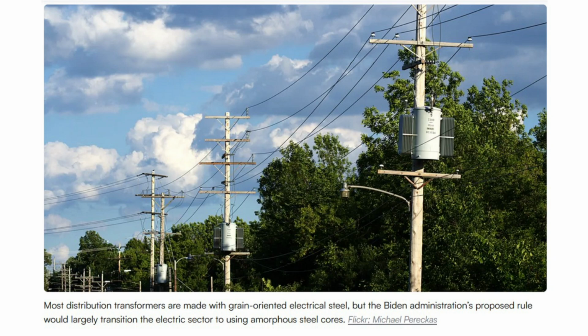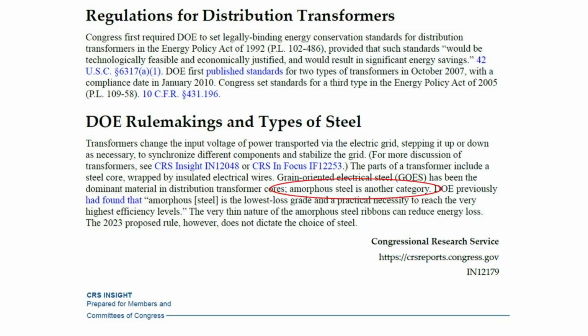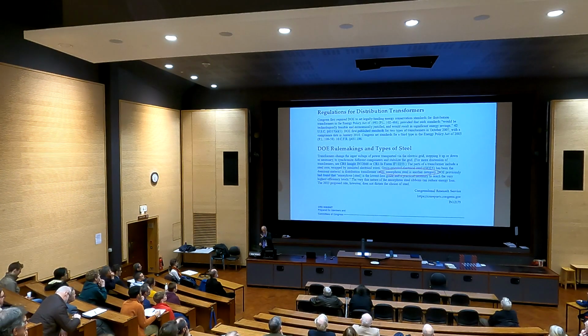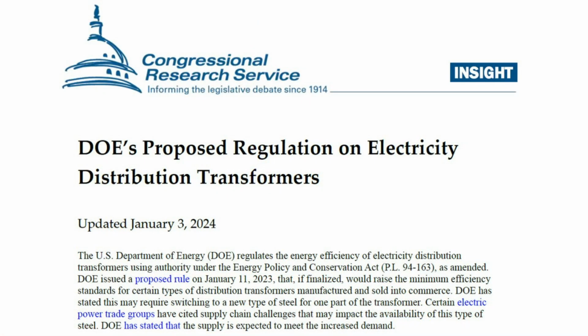And there's much interest, and has been for decades, in changing to glassy or amorphous, as they're saying amorphous steel. That's our thin ribbon I was just talking about. This is of considerable political interest. This is from the briefing notes for the US Congress. And they're talking about this amorphous steel and how they should be pressing for its use in order to reduce energy loss in the transformers. And if this were adopted across the whole system, ideally, you'd save a very high fraction of the energy loss in the core, but in cores as they're made in practical terms, you would save about half of it. And half of all the transformer loss across the US, of course, would be an enormous amount, and you're talking easily billions of dollars per year.